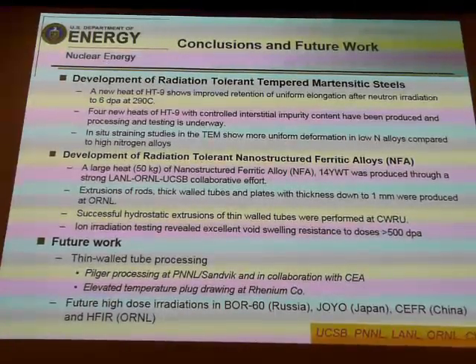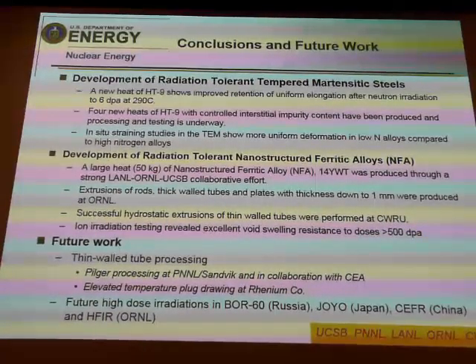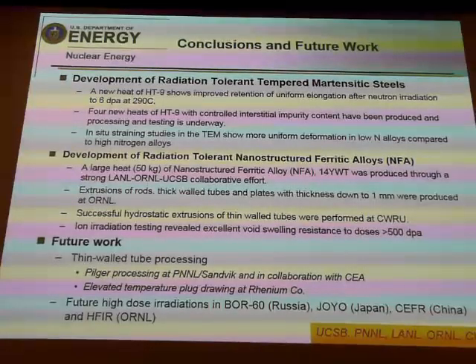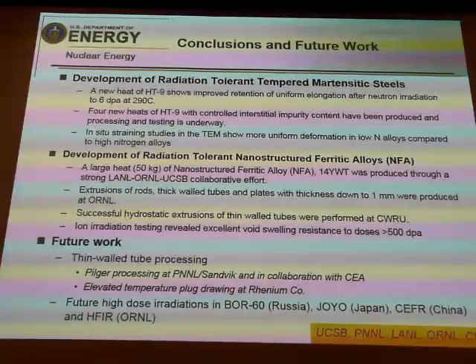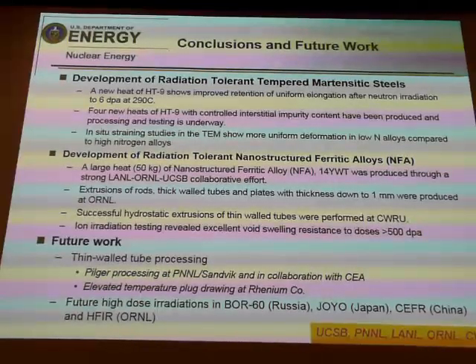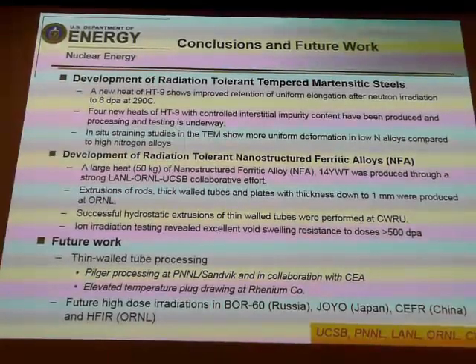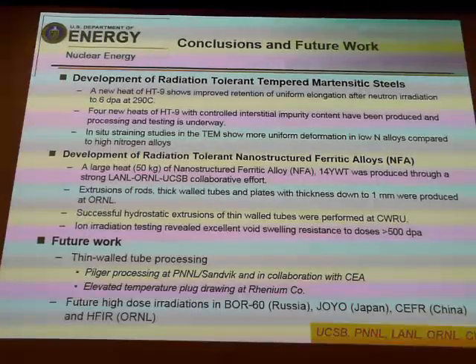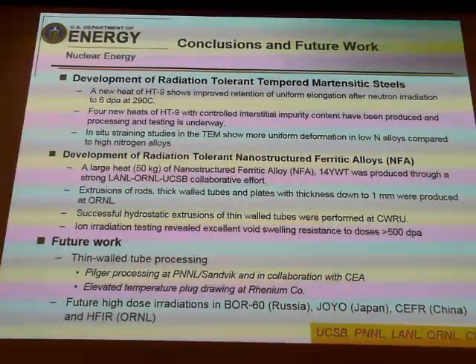But we have a large heat of 50 kilograms of nanostructured ferritic alloys that was made, and we're doing a large number of extrusions of rods and thick-walled tubes, all the way down to at least plates down to 1 millimeter. Made some successful hydrostatic extrusions at Case Western, and also as I pointed out, ion irradiation testing as well as the low temperature irradiation testing shows that these are very promising materials.